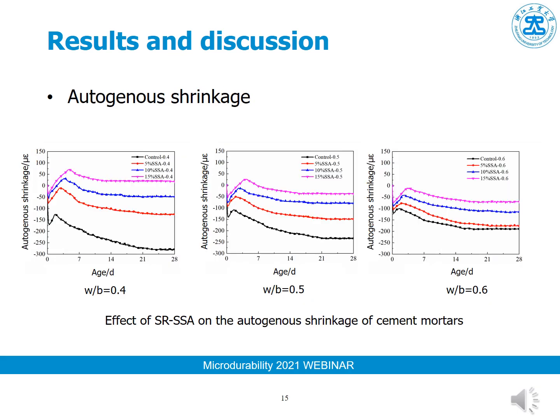Here are the test results for the autogenous shrinkage. We can see that before the age of about 3 days, the specimens expanded because of the presence of the sewage sludge ash. And after about 3 days, the specimens continued to shrink. And finally, the autogenous shrinkage was reduced by the addition of the sewage sludge ash.